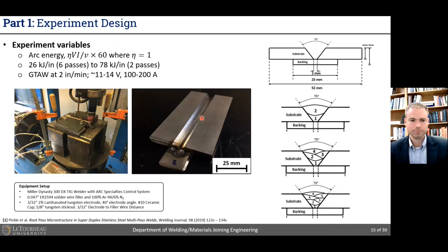So let's begin. In the first experiment, we used a standard 98% argon, 2% nitrogen shielding gas, conventional arc parameters, using a mechanized gas tungsten arc welding process and a 75-degree included angle joint design, as indicated here in the picture. We designed these welds to run in three major ways. The first was a high heat input weld with 2 passes, then a mid-range 4-pass weld, and then a low heat input 6-pass weld. And our goal was to understand how the microstructure varied with process parameters.